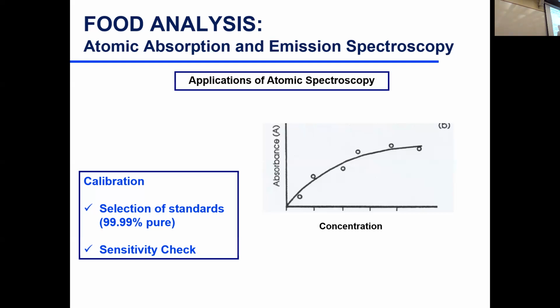Sometimes if the concentration is high, then we don't see a change in absorption that is linear. You cannot do prediction in this side of the scale. So, for example, in lab, if you are determining the concentration of calcium in cheddar cheese and you got a point of calcium way above your standard curve, so your standard curve linear range is here and you got a concentration here, you can't trust it. You can't tell if this is a correct prediction because it was outside of the linear range of your standard curve.